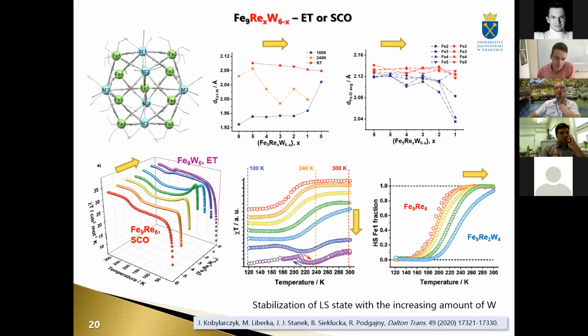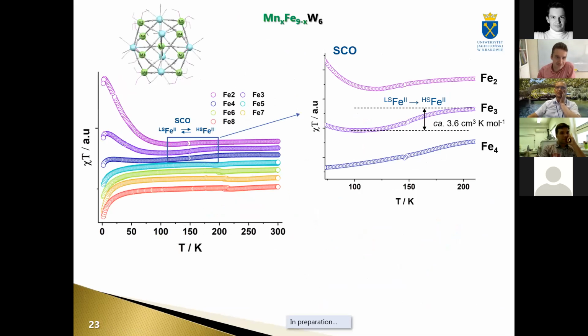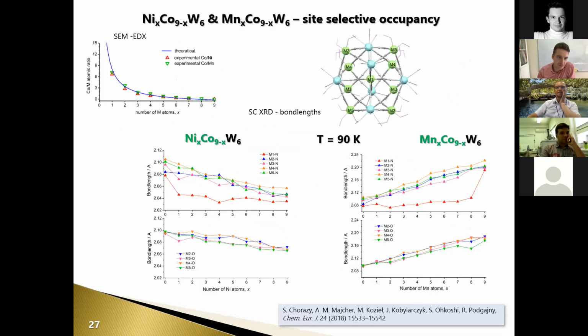You cannot, yes, I understand. I do not control the exact composition. What I do is I mix the metal ions in solutions just by calculating 1 to 8, 2 to 7 by stoichiometry, yes. By stoichiometry, okay. And then we measure the contents of each ion, of course, with some standard deviation of the technique. And then we draw the line like this, or the straight line, and judge how close is the composition in solid state against the composition in solution.